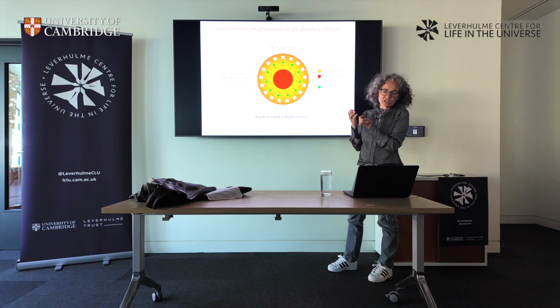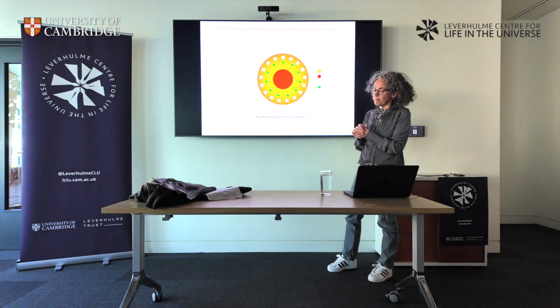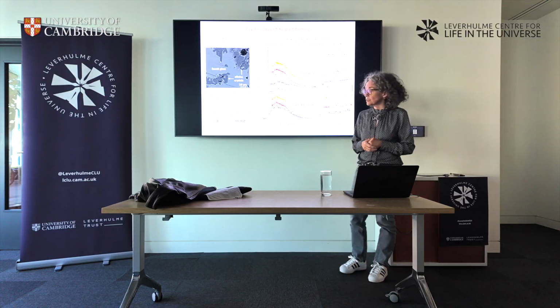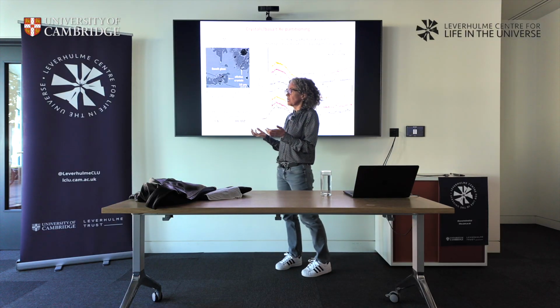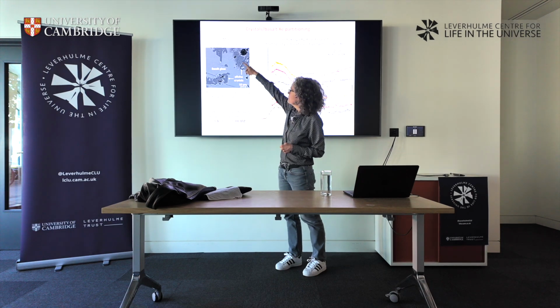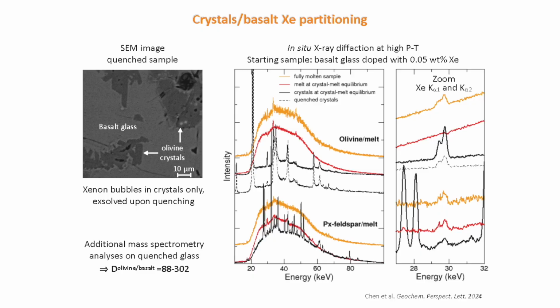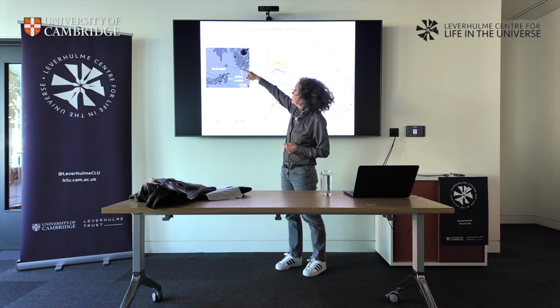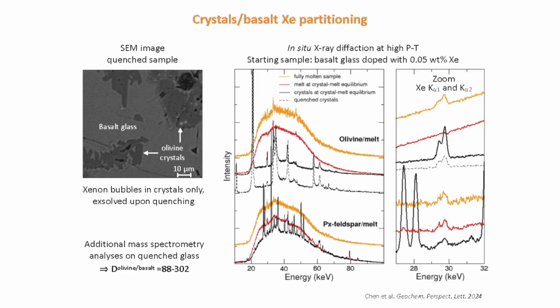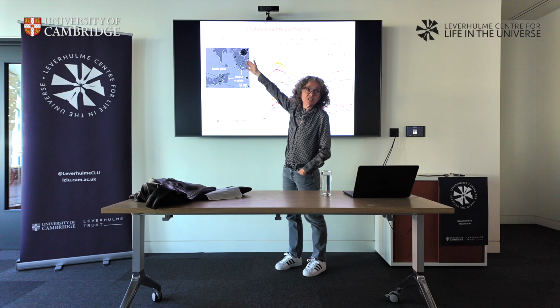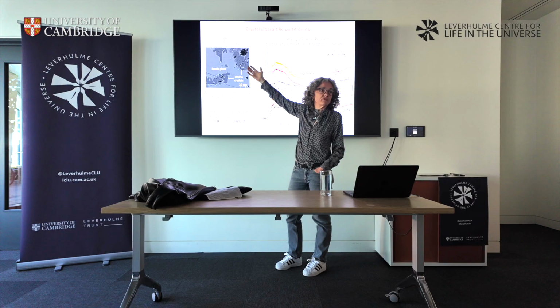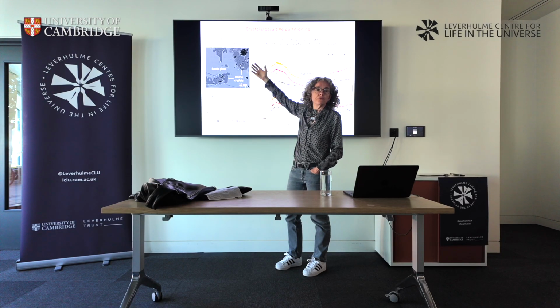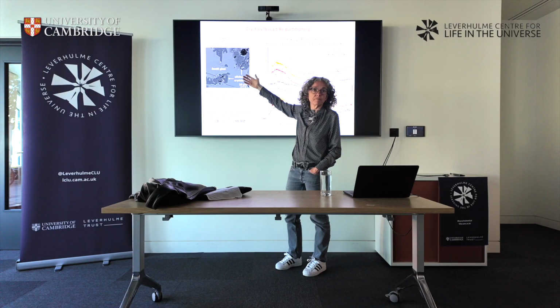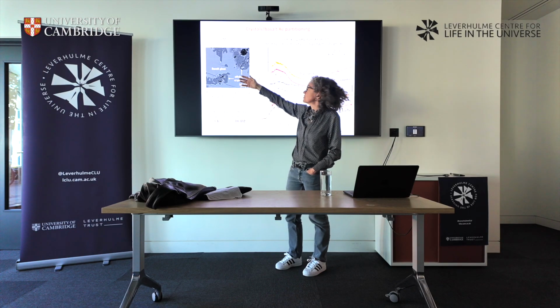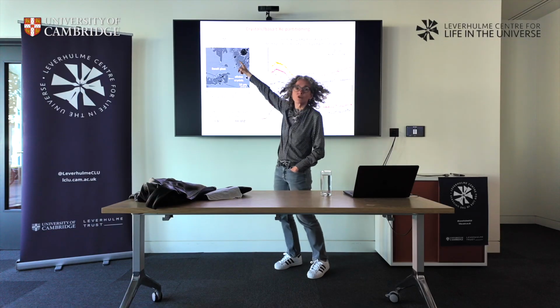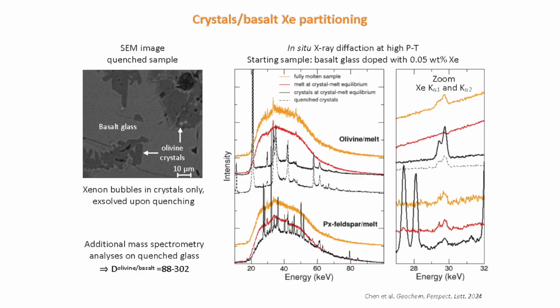So we said, okay, let's see how xenon behaves when you have crystals and melt. And the literature was extremely controversial on the topic because when you do the experiments at high pressure and you recover your sample, what you observe is something like this. You have a glass, the melt quenched as a glass, and the crystals, and well, you have bubbles. The empty bubbles are black, and the white bubbles in the SEM are white because xenon is so heavy. So you see these bubbles, and you don't know what to do with them, because you don't know if the bubbles were there all the time, or if they formed when you released temperature or pressure. So it's very difficult to know what to do with this. Some mass spectroscopists thought, okay, let's avoid all the bubbles. And others said, let's include all the bubbles. So it's very difficult to interpret.